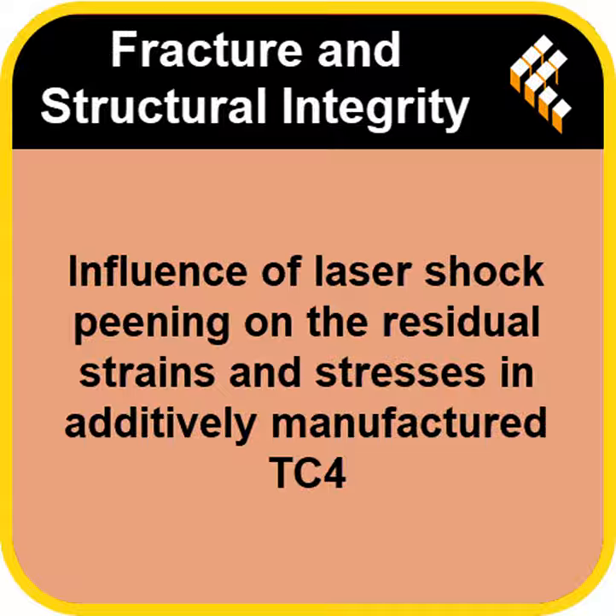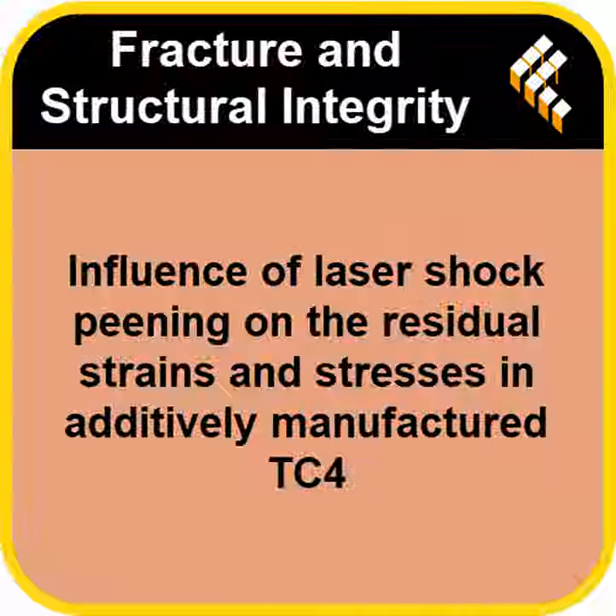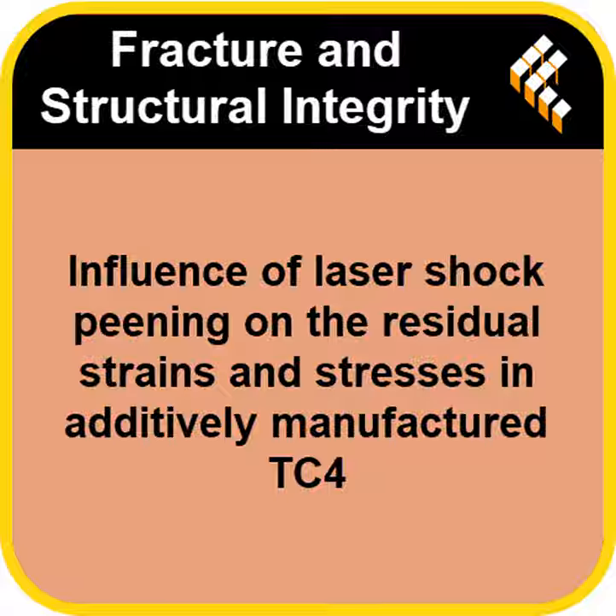Okay, so the laser treatment is done. Now the really tricky part, measuring that invisible stress locked inside the metal. How on earth do you do that accurately? You need a reliable, standardized method. They use the hole drilling strain gauge method. It's under an ASTM standard, E837.